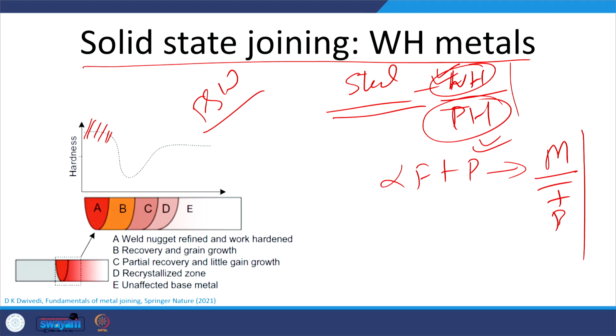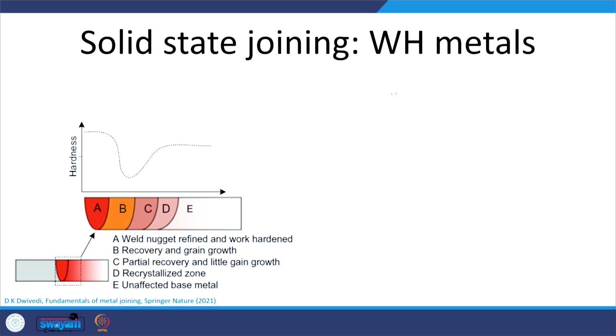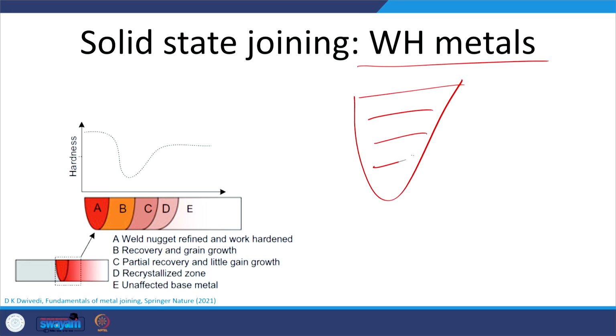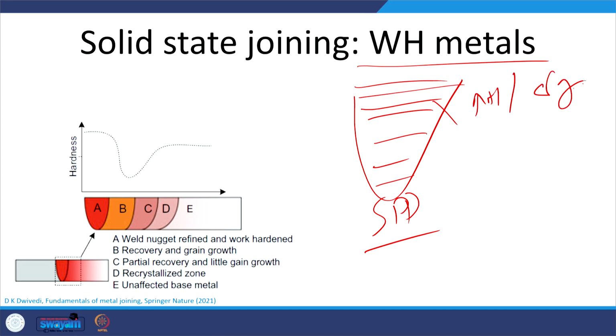Same is also true for the WH metals, since these metals rely heavily on work hardening, and since the weld nugget area is subjected to severe plastic deformation, this zone will show a significant increase in hardness and yield strength. That is why we get the significantly higher hardness of the weld nugget area.